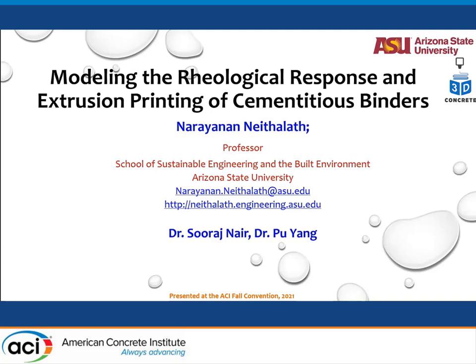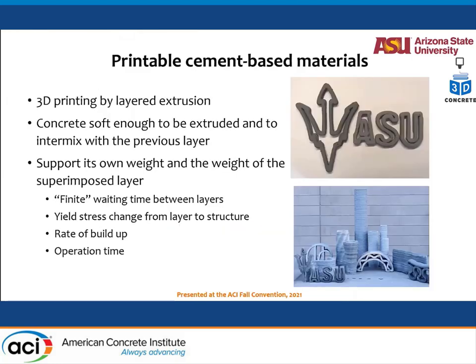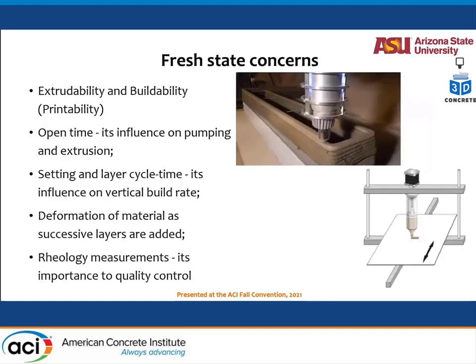This work was done by two of my recent PhD graduates. Layered extrusion is what we are talking about, and in rheology of fresh systems, what we need is concrete to be soft enough to be extruded, to intermix with the previous layer, and to support its own weight in the superimposed layer. We have issues with time — changing rheological properties from layer to layer, rate of buildup, and operation time. We also have different processes and geometries to deal with regarding the extruder or nozzle, velocities, and changes that happen in the printing process.